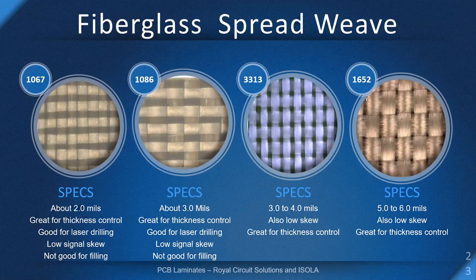Well, that's a great question, because yes, the prepreg per ply thickness will change if you have a lot of open space that gobbles up resin. So if you look at the DK/DF charts that are very common from the laminators, the laminate suppliers, they will have what they call scale flow thickness for the prepregs. That is assuming that the copper is 100%. So the thickness will be lower, and the amount etched will change that thickness.